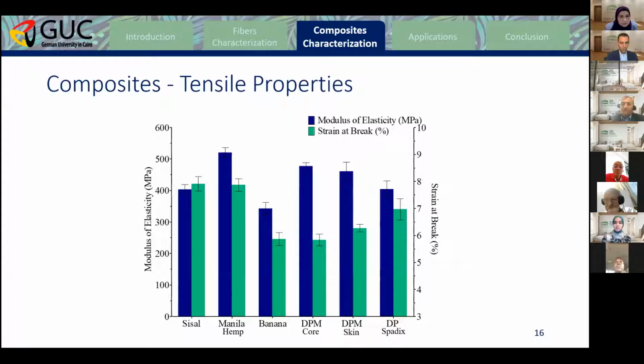This diagram shows the modulus of elasticity shown with blue bars and the strain at break in green bars. The modulus of elasticity followed the same trend as the tensile strength. However, we noticed that the strain at break of the sisal, the manila hemp, and also the date palm spadix were higher than the other 3 fibers, and this indicates high toughness of the fibers or the composites.